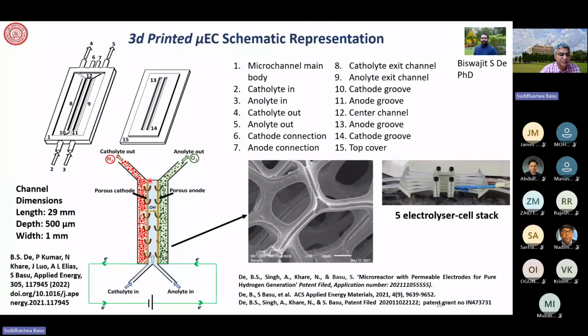This electrode is kept here, as shown by the dark yellow line on both sides, and water cannot go anywhere else. It has to move through these pores, and you have the active material on the pores, because of which the oxygen and hydrogen evolution reactions will take place, because you are applying potential for water splitting. And while doing so, they move outward and go through the channel as shown here, and in this way you are able to separate oxygen and hydrogen, with no mixing, and we have shown that you get a better current and better voltage. I mean, at a given voltage, you get a higher current.